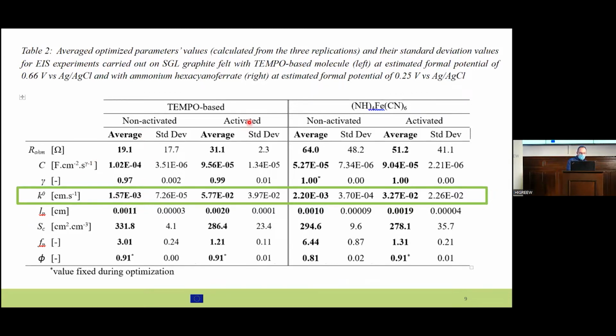So non-activated material, activated, and for the TEMPO-based and ammonium hexacyanoferrate. The non-activated material for TEMPO, for example, is around 10 to the minus 3 centimeter per second, and the activated one is a bit more than 10 to the minus 2 centimeter per second. So great, again. A similar result with the hexacyanoferrate, the second electrolyte. We see a difference between activated and non-activated, and we reach somehow the target we were looking for, 10 to the minus 3 centimeter per second.